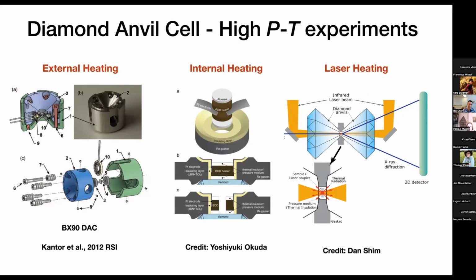For experiments that require small variation in temperature and stable heating, typically we think that external heating may be a better approach for experiments of longer duration. So that's why we invest a lot of time and effort in developing the externally heated diamond anvil cell for our experiments.